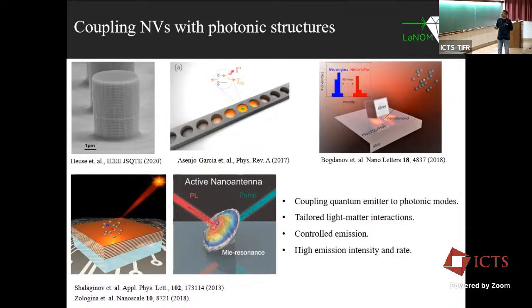There are some groups working on pillar kind of cavity structures. You have a layered structure, then you have a cavity here, or you have one-dimensional photonic cavity structures or nanobeam cavities. And people are also using silver cubes trapped with an NV center in a nanodiamond here, trying to modulate the emissions. There are some groups working on hyperbolic metamaterials. Basically, these are metal-dielectric stacks coupled with NV centers, or using the Mie resonance of micron-sized diamond particles.